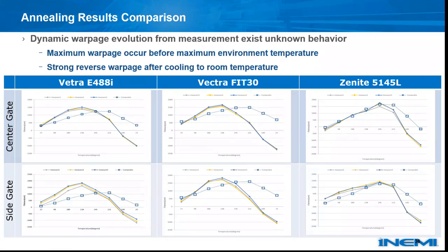However, the experimental results show the maximum flatness occurred before the coupon was heated to the maximum temperature, and the warpage quickly deformed to the upside direction, and the negative flatness is even stronger than the magnitude before the coupon is heated. So we suppose there are some conditions or criteria that happen in the experiment, or some physical model such as a nonlinear effect that is not considered in our simulation now. So we decided to move to our main target of circuit validation. Next.